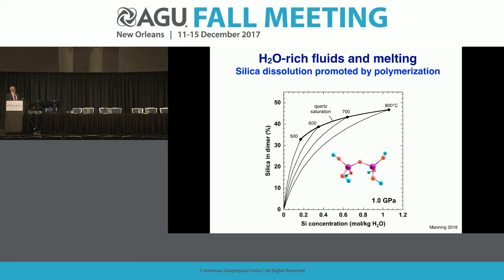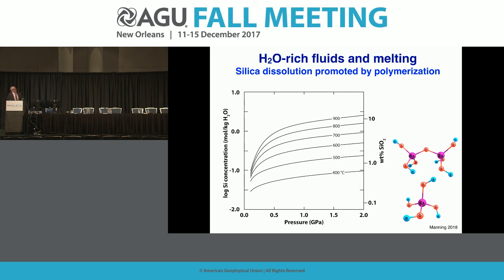Polymerization is strongly temperature and pressure dependent, so we now have thermodynamic data we can use from our solubility experiments and from Raman spectroscopy. We can calculate the thermodynamic properties of the dimer and show that at quartz saturation, the abundance of the dimer would be along this black curve, or below quartz saturation, the dimer formation would be increasing like this. So basically, in all of these solutions, the silica is present as two species predominantly, a monomer and a dimer. So if that's all right, we should be able to predict solubility at a range of conditions, and we try that, and we do.